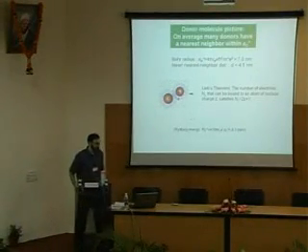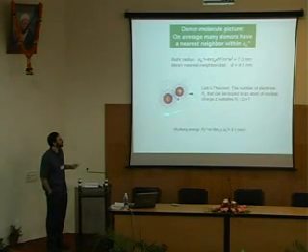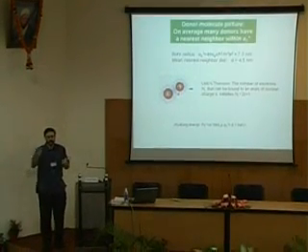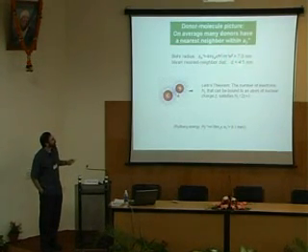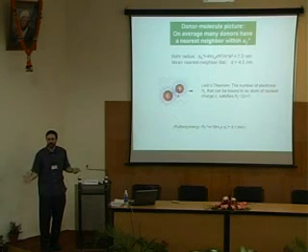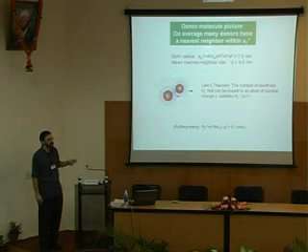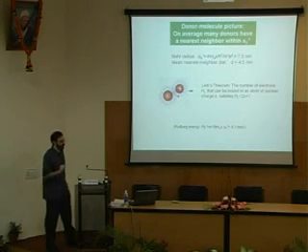So with the help of my theory colleagues like Carlo Piermarocchi, he sat down, patiently listened to me talk about the data, and said, Stuart, you should think about nearest neighbors, because even though it's complicated, there's lots of randomness going on. If you look at the average distance to nearest neighbor, just statistically, knowing the density of our sample, it turns out to be 4.5 nanometers. The Bohr radius for the sample is fairly large, 7 nanometers. So on average, every dopant does have a nearest neighbor within its Bohr radius. So it's certainly possible to say there are maybe lots of dopants that are coupled to their nearest neighbor. Now it's fair to call them a molecule. So that's why the title of this talk is Donor Molecules.